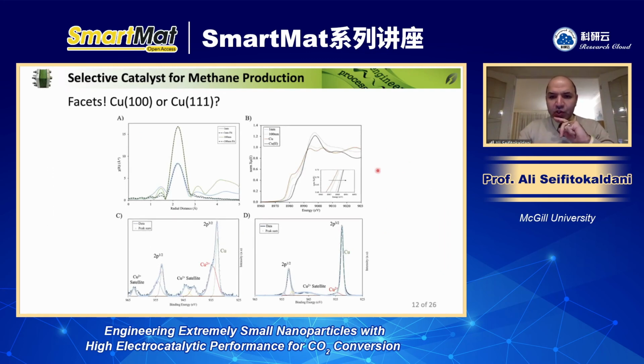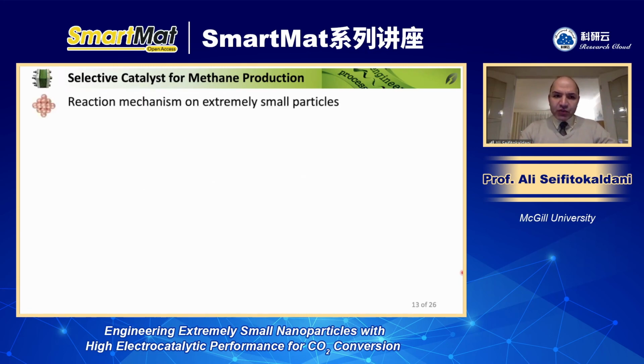I just forgot to mention that we also ran different characterizations to further investigate the crystallinity, including XAS, X-ray absorption spectroscopy, both in situ and ex situ, and also XPS. XPS showed that for a small particle like 1 nanometer, we mostly have copper 2+ because it's easily oxidized. And the ex situ XAS was also proving the same thing. But as soon as we run the experiment and we apply the potential, then all of them go back to metallic copper, so copper 0. So I just forgot to talk about that.